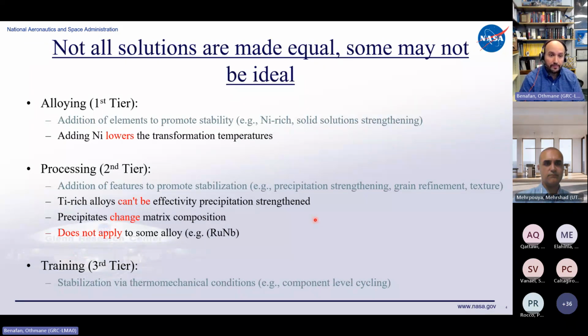For instance, if you go to tier 1 and we do solid solutions, sometimes by adding nickel to the composition to make it stabler, you lower the transformation temperature. So you take a knockdown on transformation temperatures. As we know, the more nickel you add, the lower the transformation gets. On the processing side, tier 2, you can do features like precipitation strengthening.